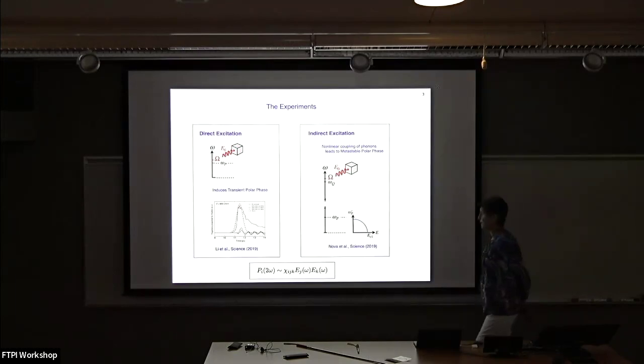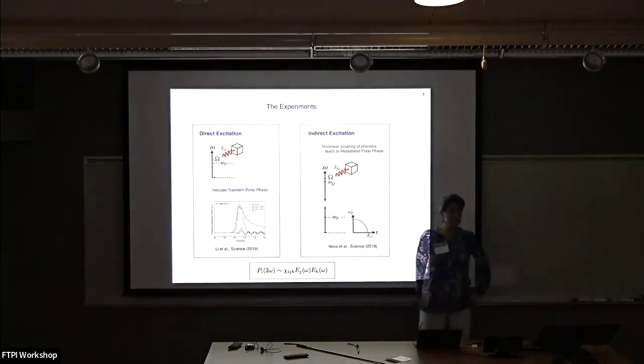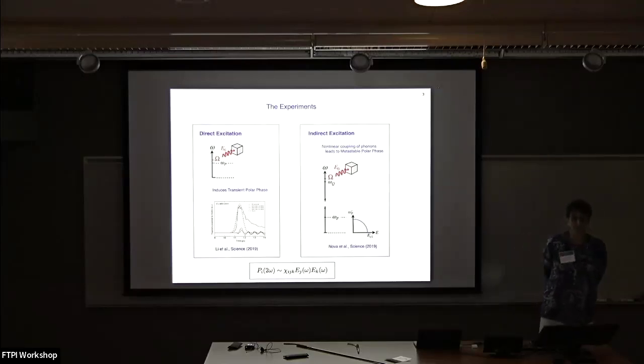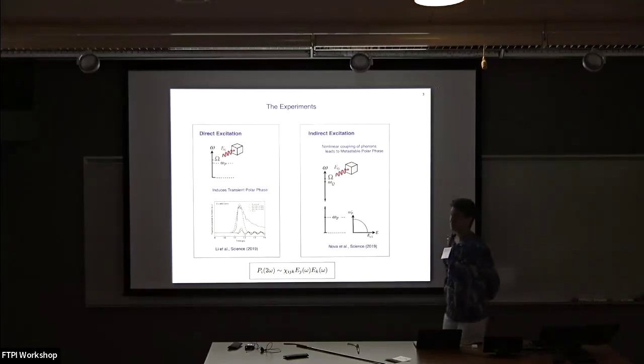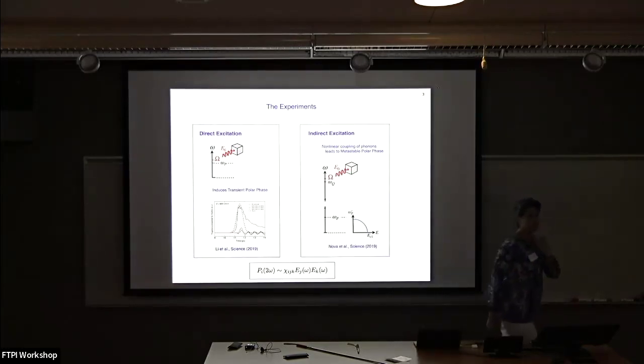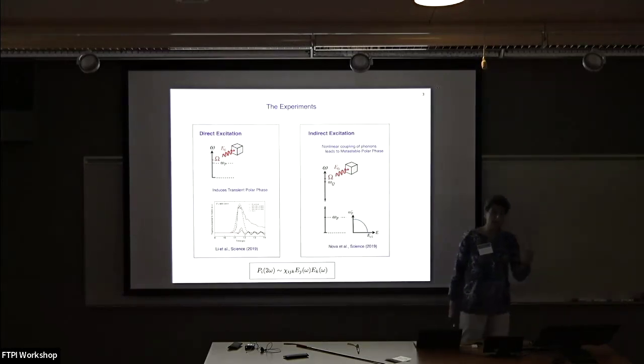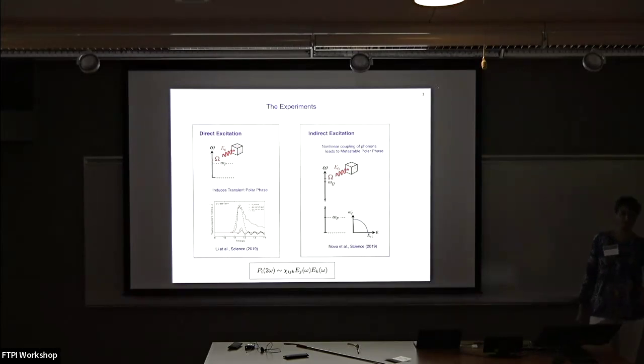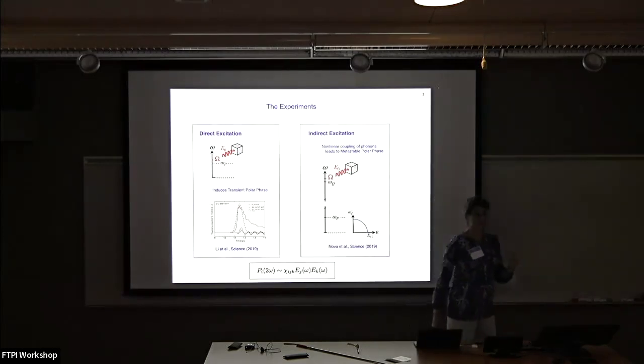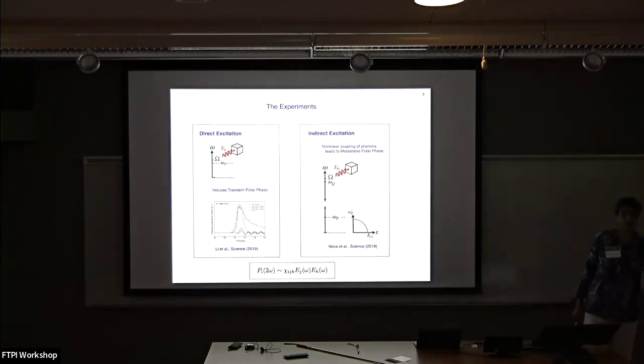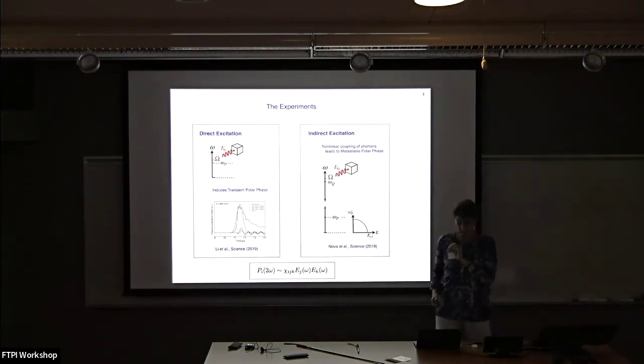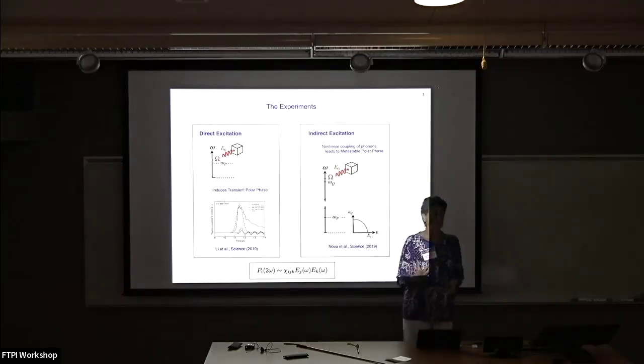that meant that they had actually had a light-induced ferroelectric transition. Now, more recently, these are terahertz pump-probe measurements. More recently, people have developed ultrafast time-resolved diffraction measurements. And in fact, in his talk, Peter showed us one from the Slack group, where what they're able to do is within a pulse width, that means within 10 to the minus 12 seconds, they're able to take a snapshot and look to see what the structure is. So that's how people can characterize that now. So these are the sorts of measurements that inspired us to think about light-induced phenomena.